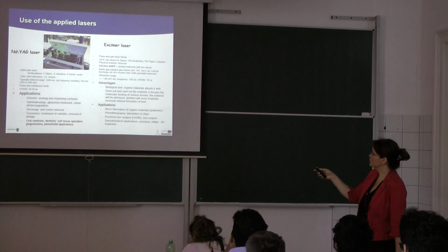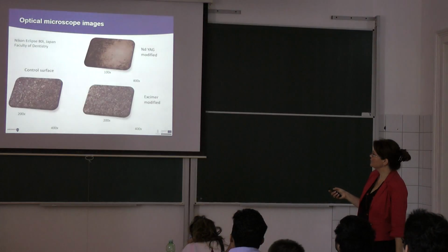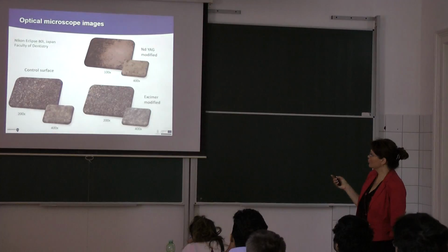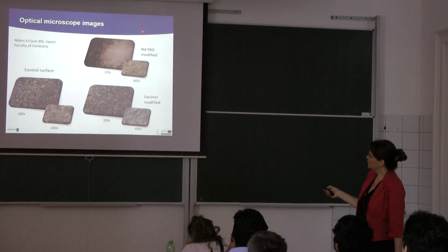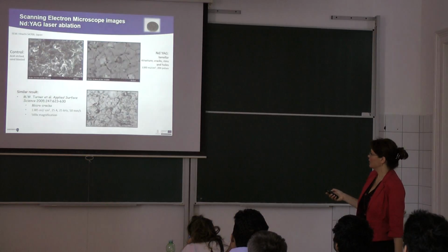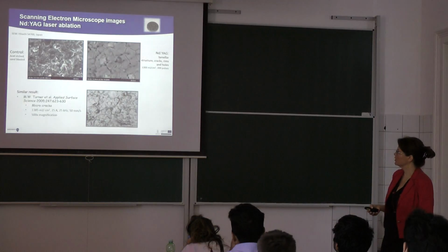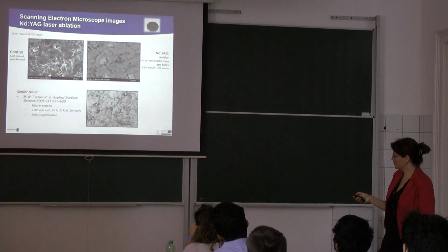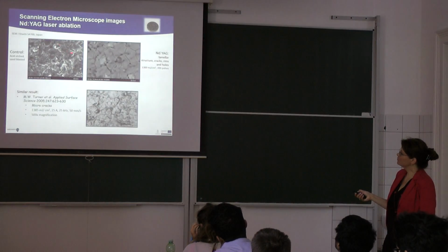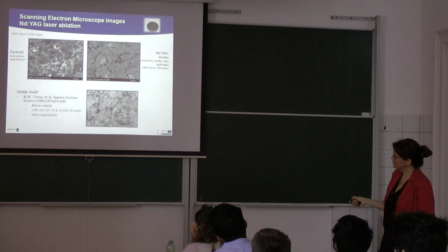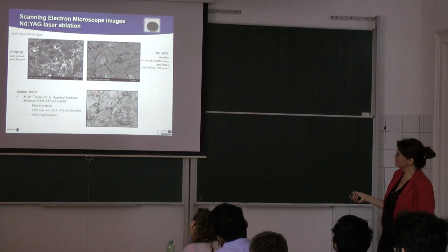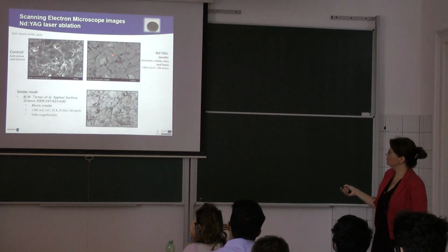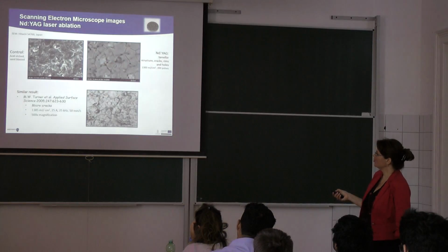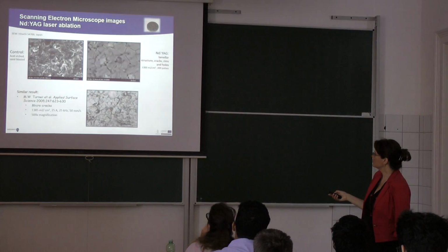What we have found, of course, you know the difference between the neodymium and excimer laser. Unfortunately, in respect to the control surface, we had much smoother surfaces, which was not our goal. We wanted a rougher surface for the osteoblasts, but okay, this was available for the environment. We also compared with other studies, and as you can see, Turner in Applied Surface Science in 2005 saw the same cracks with the neodymium laser ablation, which is not good because if you have these cracks, they can come down and make a toxic effect on the dental implant.